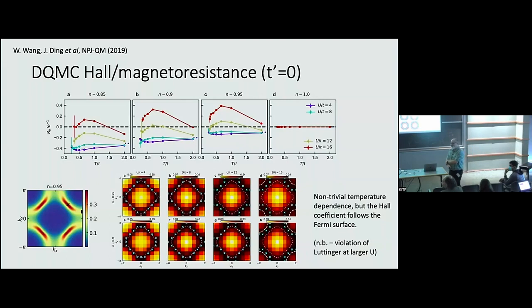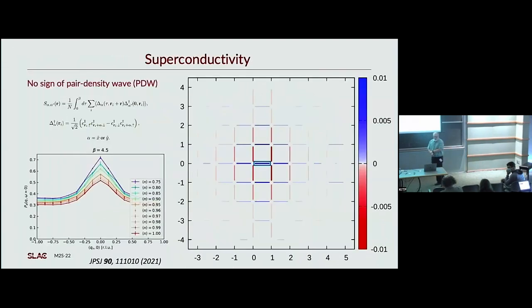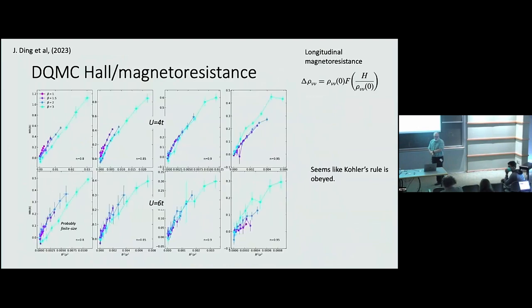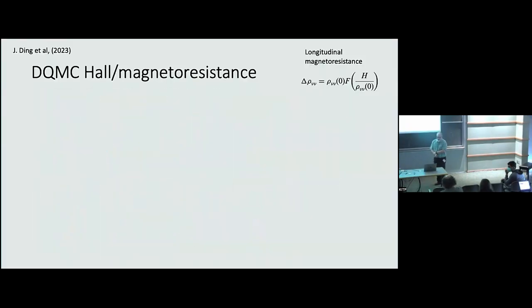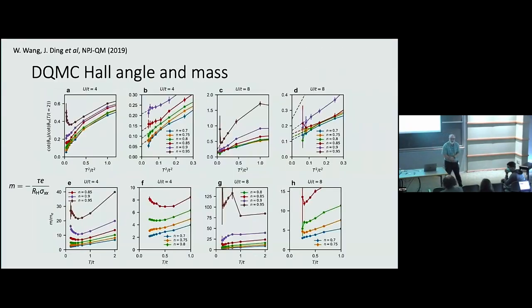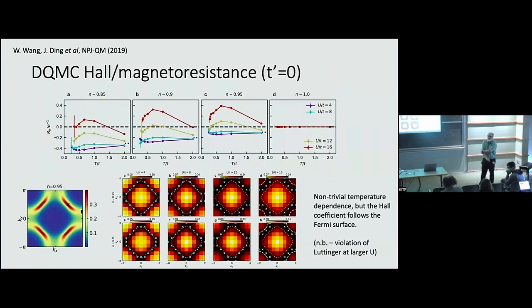Go ahead. No, I'm going to start arguing. Around the same time our paper was published, there were also some cold atom experiments where they tried to study the same problem, and they're doing this in real time, no analytic continuation. If you look at their data, there also seems to be a bit of an offset in the extrapolation to zero temperature. So it's a combination. Of course, the analytic continuation doesn't help there. From the cold atom experiments, it seems that there's really something causing this offset.